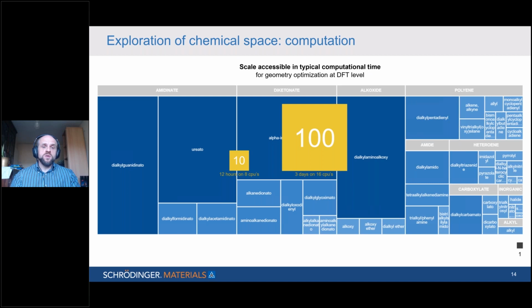What can we compute? Well, if we're doing, say, density functional calculations, so quantum mechanical calculations, we can easily compute 10 precursors in a day, say 12 hours on 8 CPUs. If we wait a little longer, we can run 100 precursors in 3 days on, again, modest computational resources. And if we have more resources or we wait longer, we can do DFT optimizations of maybe more precursors, but that's kind of the order of magnitude that you can easily do. You can easily scan through 100 precursors at quantum mechanical level.